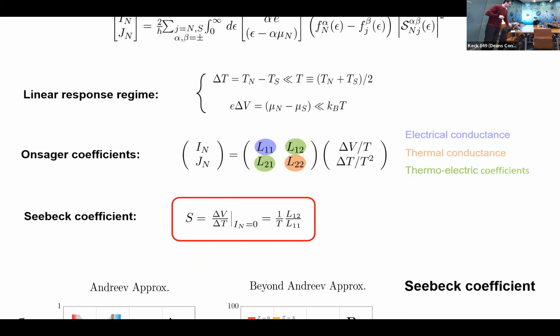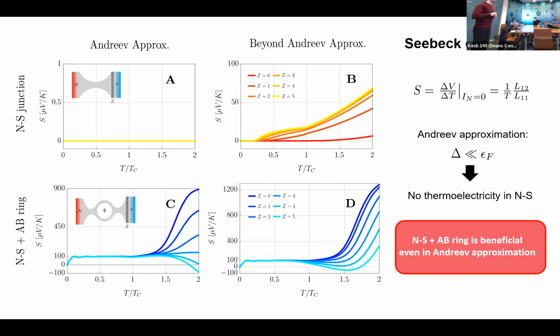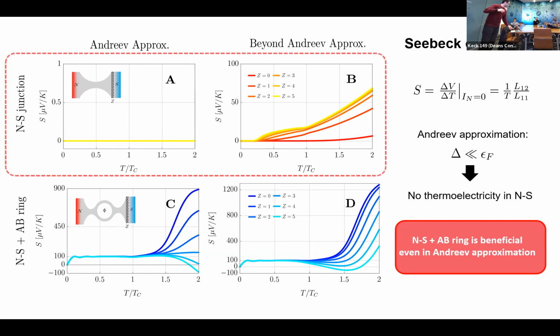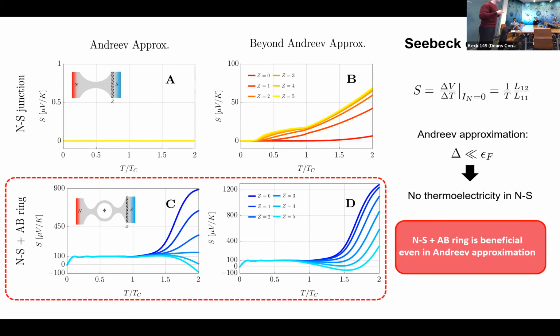So here I present the results that we obtained for the Seebeck coefficient in the linear response regime. In order to single out what the role of the ring is for our system in producing thermoelectrical properties, we distinguished between two different configurations. A first configuration in which we don't have the presence of the ring, so the system is just a normal-superconducting Josephson junction, and this refers to the top panels A and B, and a configuration in which we do take into account the presence of the ring, in which case the results correspond to the bottom panels.